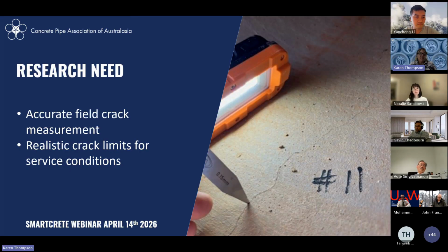So what we're hoping for is accurate field crack measurement being possible. That's our dream. And that's where Yancheng and his team at UTS offered up the idea that deep learning assisted computer vision could be a game-changing alternative to current CCTV monitoring of installed pipes. And then asset owners need to have an improved understanding of the mechanism of cracking in concrete pipes. The crack initiation and propagation needs to be better understood, and how it differs from ordinary concrete due to the low water cement ratios in the product, the level of compaction that's utilised in the manufacture of the pipes, and the very small diameter of steel that's incorporated compared to normal steel reinforced structures.